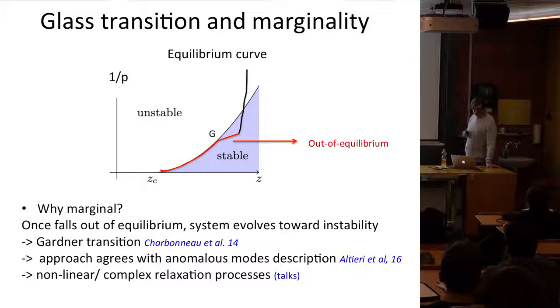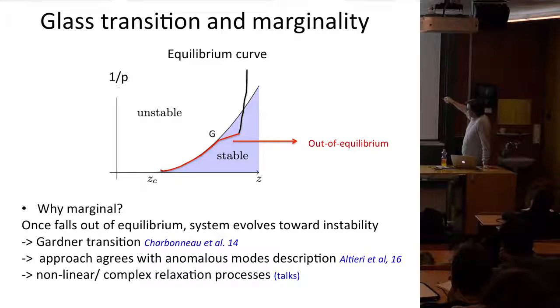Okay, so this is the last slide I want to comment on before I take the break. So here again, you could ask, why is it that this colloidal glass is really marginally stable? And the results of Charbonneau and co-workers, Francesco, Parisi, and so on, support the following scenario in this phase diagram. So that's the equilibrium curve. As you increase the pressure, at some point you would hit that curve, modes would become stable, and the dynamic would become activated. You can still equilibrate the system because those barriers have a finite height, but at some point you become unstable. This point where you become unstable would depend on your quenching rate. So if you quench rapidly, it would be here. If you quench slowly, it would be here.